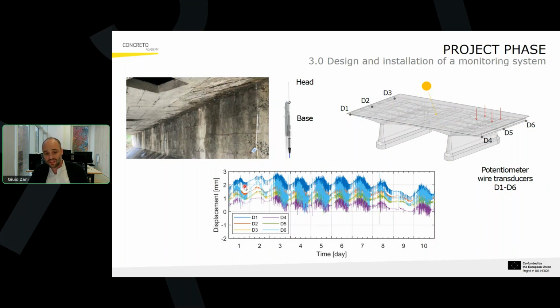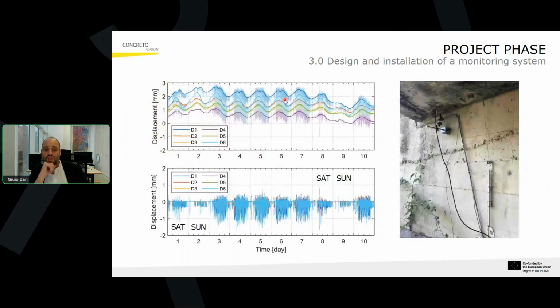This is due to the fact that even though these devices were conceived and designed for static monitoring, we recorded the information at a sampling frequency of about 40 Hertz, collecting also some information associated with the passage of moving loads, so the passage of vehicles. At this point, we decided to run a moving average to extract the behavior associated with thermal loads, and by operating a difference between these two measures, we obtained the displacement associated with the variable loads alone.